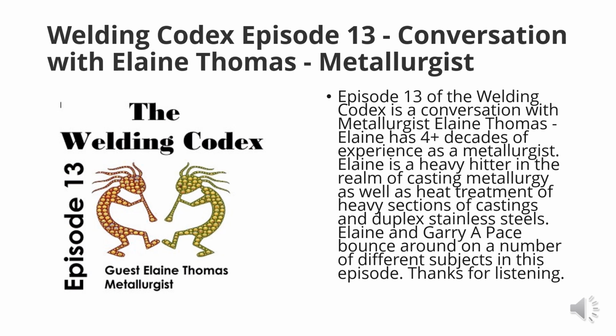It breaks back up into the individual atoms, and then you water quench it to freeze those atoms in place and not let them reform into sigma. That's such an important step, super important. If you don't do that, the casting won't live to see tomorrow.